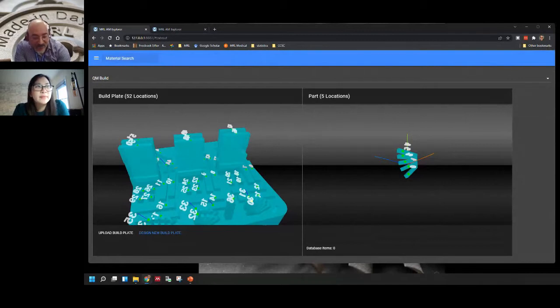So that's a very loaded question, because it has a lot of layers in it. So let's talk about the texture first. The texture prediction is related to the thermal profile, which is planned anywhere within the part. So if there is variability in the thermal profile in the part, then the texture prediction will yield that. The measurement itself for the blind testing was selected to be in the bulk of the material, and this is where we identified by the samples that was extracted that you saw in the earlier slides.